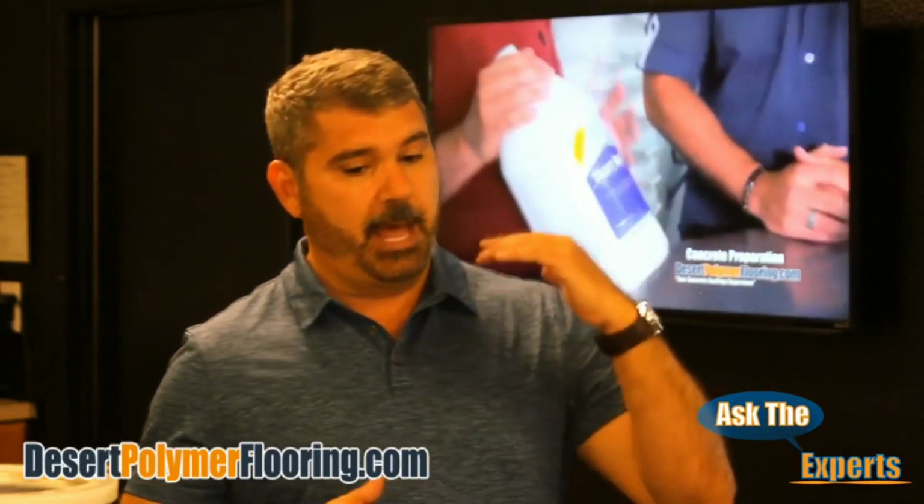Now, people have always asked this question: can I recoat with Poly 250? I've been asked that question. I don't really know the answer, so this is probably a good time to find out. Sure. You can recoat with Poly 250 indefinitely over itself. We always recommend that they clean the surface and do a light sand before recoating any two-component materials. But Poly 250 will bond over itself with 50% acetone added to it. And so the bond is there, and you can recoat over Poly 250 with no problem. That's awesome.